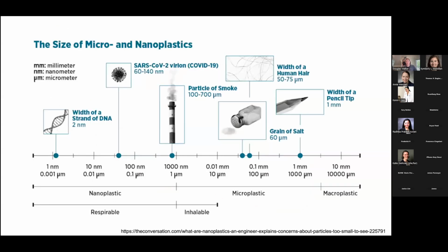And in fact, from an exposure perspective and what we can measure in humans, we're interested in things that are smaller than 1 to 5 micron. For context, a particle of smoke may be about 100 to 700 microns. The SARS-CoV-2 virion is about 60 to 140 nanometers. The width of a strand of DNA is about 2 nanometers. The measurements we're applying allow us to measure microplastics from a confirmed 300 nanometers and larger, but we may think that due to some aggregation or clumping while we're manipulating our samples, we may be able to measure even down to 100 nanometers or smaller. I'll talk about that more in a few slides.